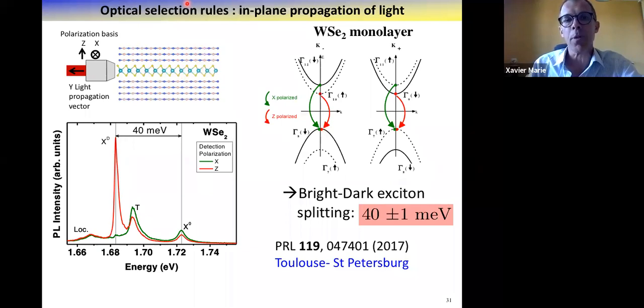Usually when you do an experiment, you do not use this crazy idea to detect by the edge, as I will show now, but what we usually do is you excite with a light which propagates perpendicular to the monolayer, which corresponds to an in-plane polarized light. And with in-plane polarized light, considering the symmetry, you can analyze from group theory of the conduction and valence states, indeed you will have a bright exciton connecting the same spin state from conduction and valence states.